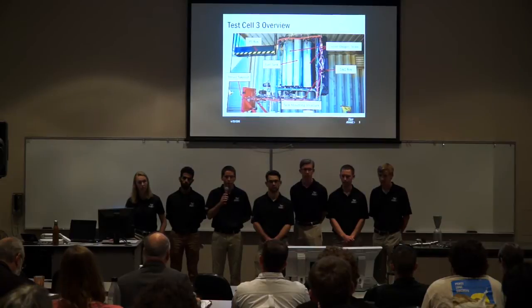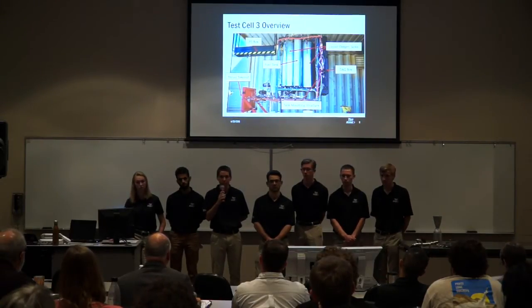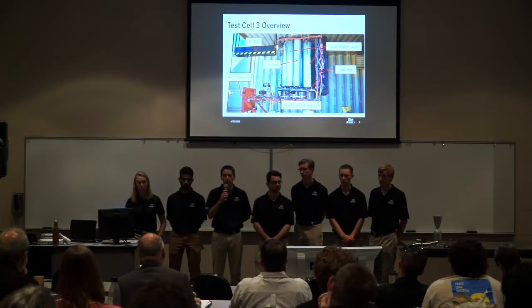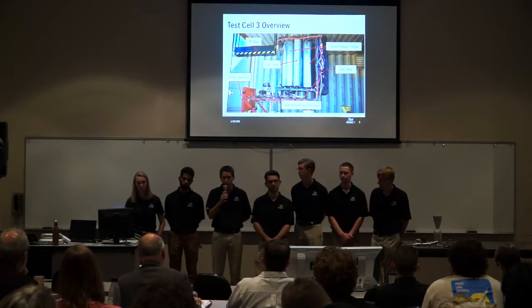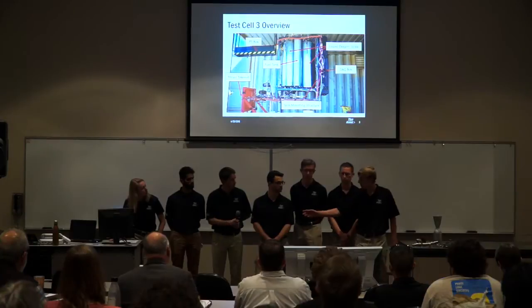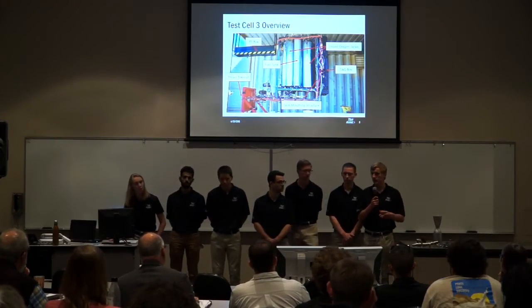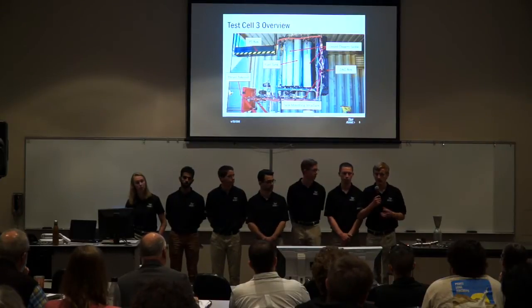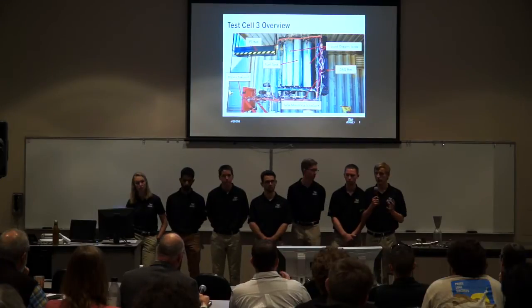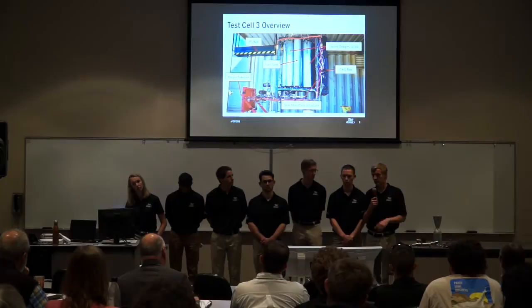But it took us all semester to get to a point where we can now test the chamber, and now we're seeing that it's not performing as we would like it to. So there are plans to reevaluate and make changes, and possibly do some throat inserts or investigate new building materials. Another thing is we also don't know if that erosion is steady state or transient, because on startup we kind of set the walls of the chamber on fire, and then we start up and that's pretty rough. Hopefully in steady state the erosion decreases, and that's one of the things we look for.